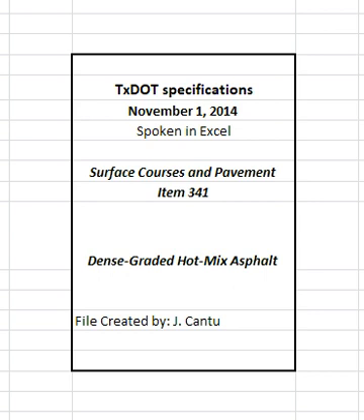The asphalt binder content established for JMF2 is not required to be within any tolerance of the optimum asphalt binder content established for JMF1, however, mixture produced using JMF2 must meet the voids in mineral aggregates, VMA, requirements for production shown in Table 8. If the optimum asphalt binder content for JMF2 is more than 0.5% lower than the optimum asphalt binder content for JMF1, the engineer may perform or require the contractor to perform TEX-226-F on Lot 1 production to confirm the indirect tensile strength does not exceed 200 psi. Verify that JMF2 meets the mixture requirements in Table 5.